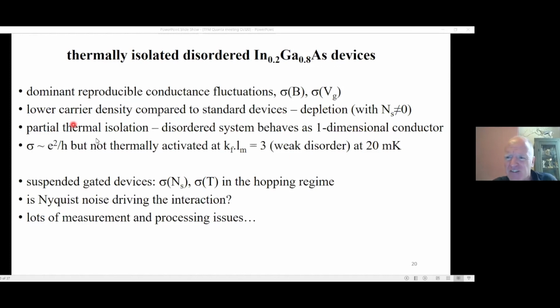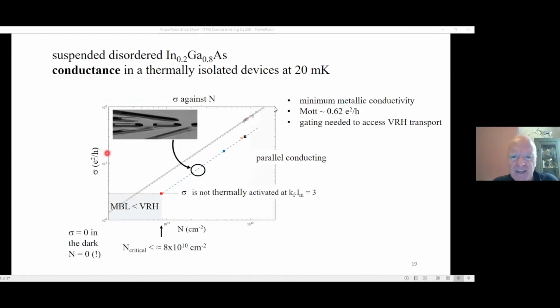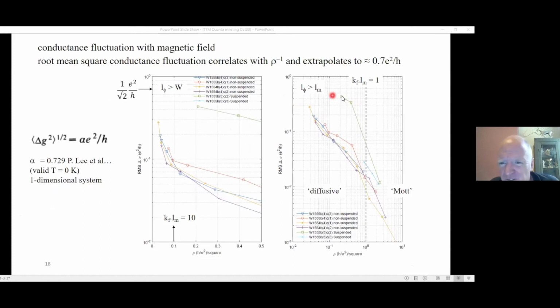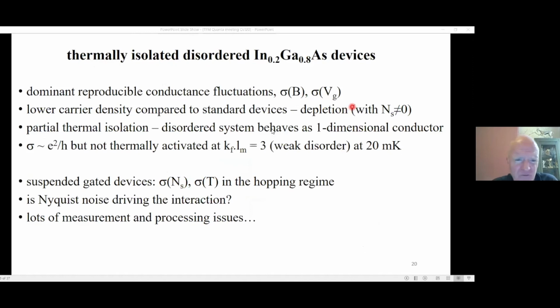I forgot to mention that, if I go back, we see a large difference. This is the thermally isolated device. This is the non-thermally isolated. I forgot to make that clear in this. So we've got a large difference in how the root mean square conductance fluctuation behaves between the freestanding and the non-freestanding. Conductance is about e squared upon h, but it's not thermally activated. We're still in that weak disorder at low temperatures, although we put all that disorder in.